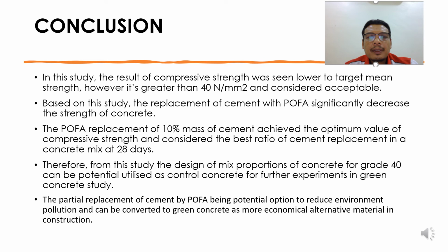Based on this study, the replacement of cement with POFA significantly decreased the strength of the concrete. The POFA replacement of 10% mass of cement achieved the optimum value of the compressive strength and is considered the best ratio of cement replacement in a concrete mix at 28 days.